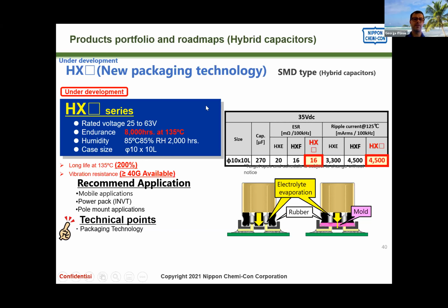Even on this capacitor, from an endurance standpoint, we're looking at 8,000 hours of endurance, up from 4,000 hours. So double the endurance without any change internally on the capacitor itself. The only change is that epoxy layer. And of course, we're also looking at polymers, where we can perhaps control or minimize the amount of humidity intrusion into that element.